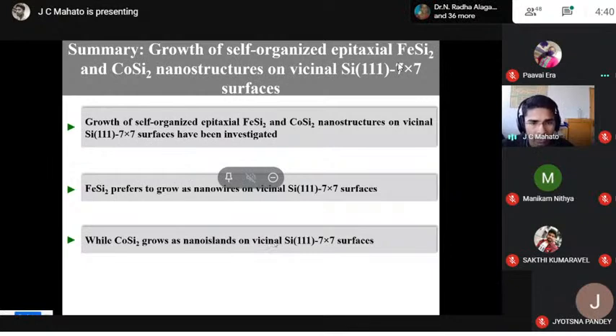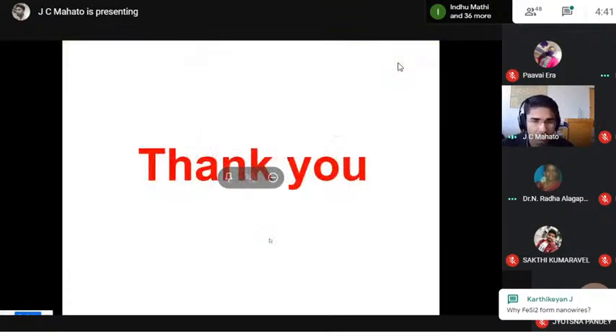So in conclusion, I would say that we have investigated the growth of self-organized epitaxial iron disilicide and cobalt disilicide nanostructures on the same surface, that is the vicinal 111 7 by 7 surface. Iron disilicide preferably grows as a nanowire on the vicinal surface, while the cobalt disilicide grows as a nano island on the vicinal surface. And here we use the fact that the iron disilicide is thermally stable at the growth temperature of cobalt disilicide. I would like to acknowledge my collaborators and seniors, and thank you for your kind attention.